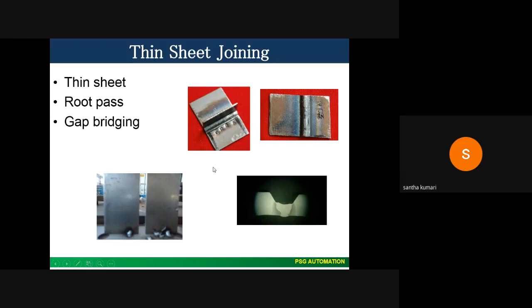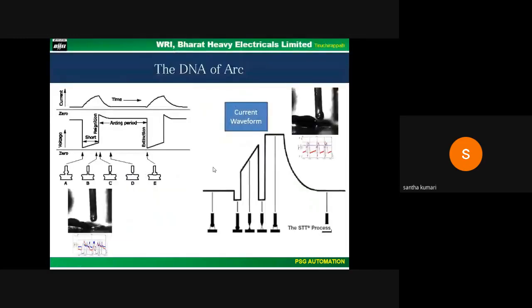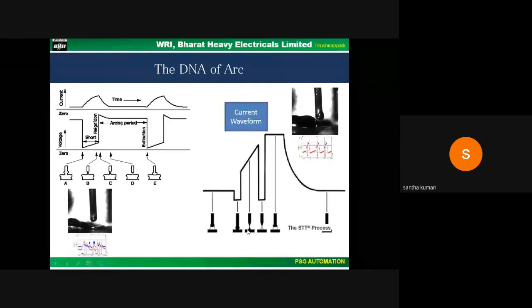With conventional sources it was not possible to lower the current in the short time necessary, as it does not permit the rapid control of the current due to the mass of the transformer and the downstream choker. The case is different with the inverter power sources, because here the inductivity can be set electronically and can, in the event of a short circuit, be even fully shut down, which means that only the inductivity in the welding leads remains active. So the rise and fall of the current during the short circuit phase and the reignition of the arc can be fully stabilized very quickly with lesser and even no spatter.